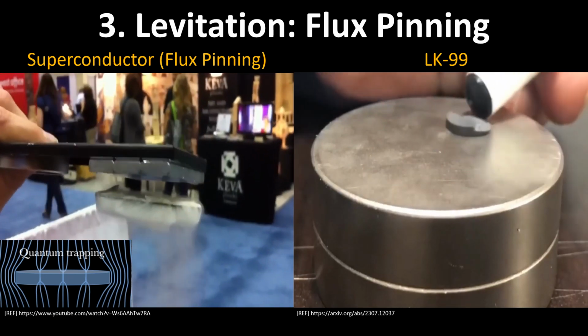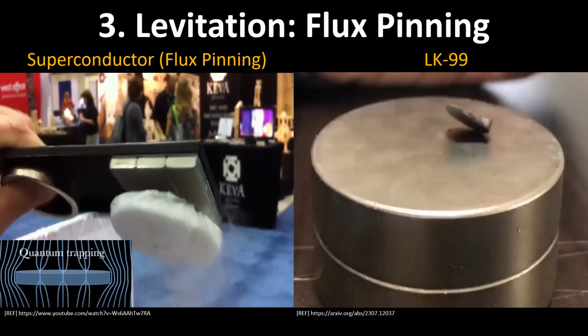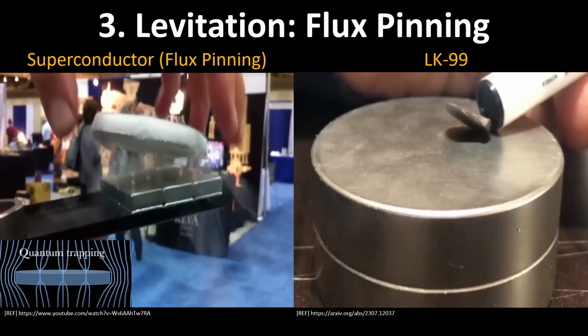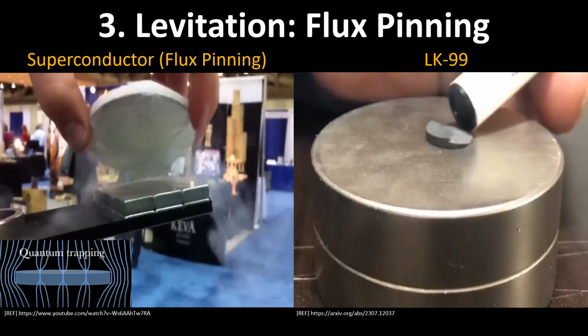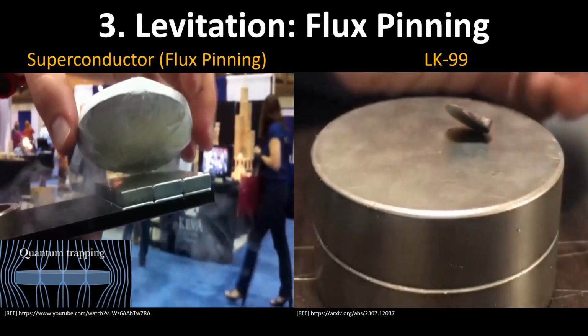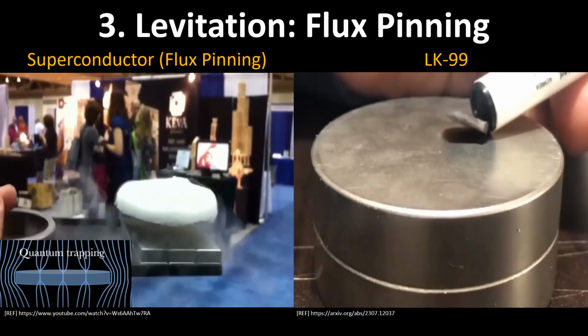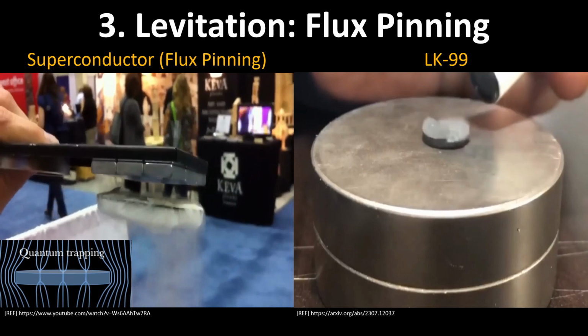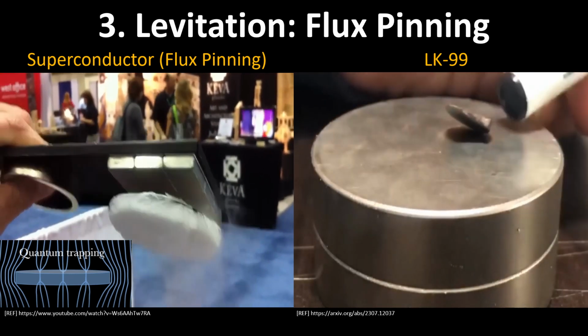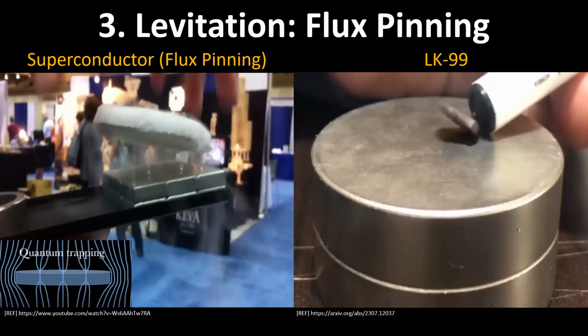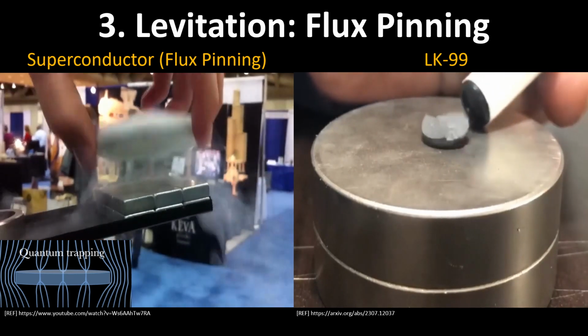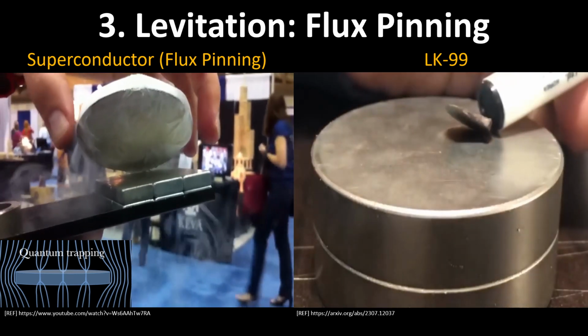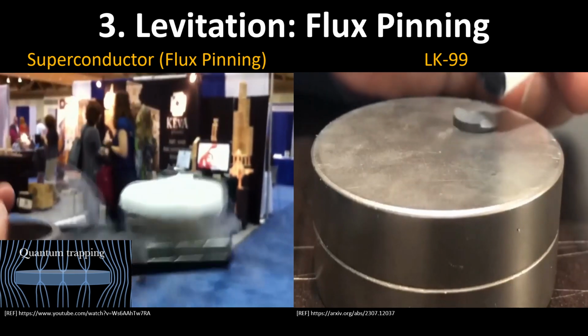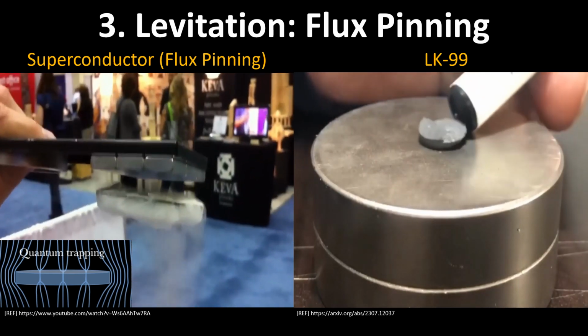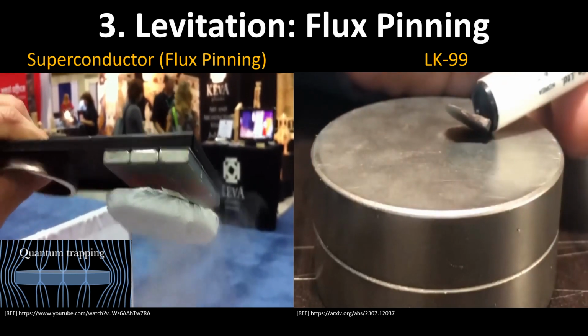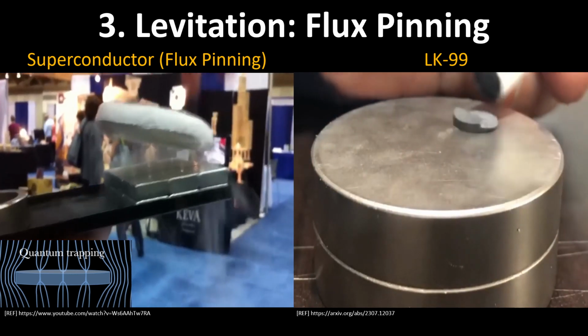The material is not fixed when an external magnetic field is applied, but rotates and sticks to the permanent magnet on the bottom. This is a rare phenomenon in superconductors, particularly in a situation where there seems no particular change in the experimental environment. The collapse of flux pinning and sticking to a permanent magnet is not typical in ordinary superconductors. Of course, it could also be an issue caused by the purity of the material, so it seems that more measurements and verification based on data will be needed in the future.